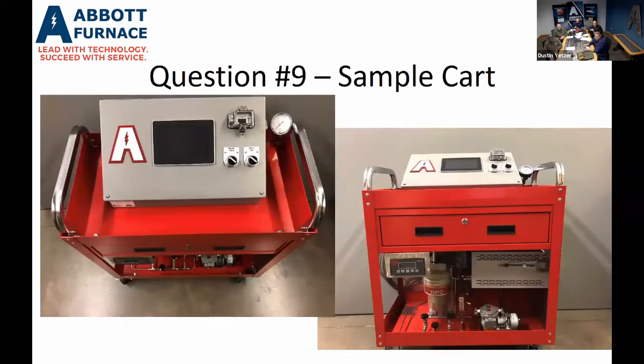We do have an atmospheric cart here at Abbott Furnace that we use. You see it here in the picture. It does measure the hydrogen, the oxygen, and the dew point inside your furnace itself. This all correlates when you have discolored parts or something going on with your furnace. You've got a green belt perhaps, or discolored parts that we talked about earlier. We've got to figure out if it's air or water, where it's coming in at, and what we've got to do to balance that furnace to get good parts.